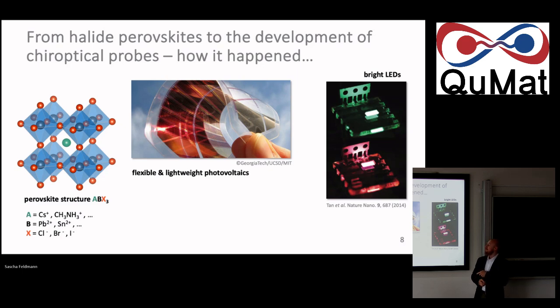You have a cubic crystal structure here. You have corner-sharing octahedra of these lead halide octahedra, arranged in a cubic fashion around the central A-site cation. That could even be something organic, like methylammonium as a cation. You put it together, spin coat or drop cast your little film, and you get a remarkably efficient, even flexible, ultra-lightweight and thin solar panel or LED out of it. And that's really still magical to me, how that can work so well.